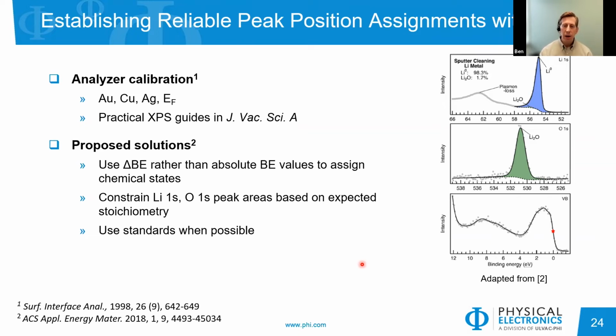Some other things you can do: rather than looking at just the absolute value of the peak position, you could look at the energy separation between, say, a lithium and an oxygen species. And what's really nice, if you had standards you could start with, then you can look at your standard materials, identify the relative peak heights and the relative separations between different materials of a given state, and then use those constraints to help you identify the peaks in your own material.